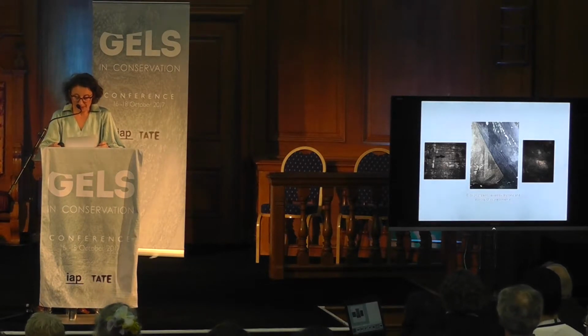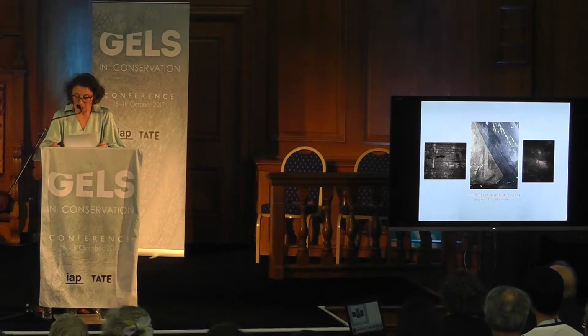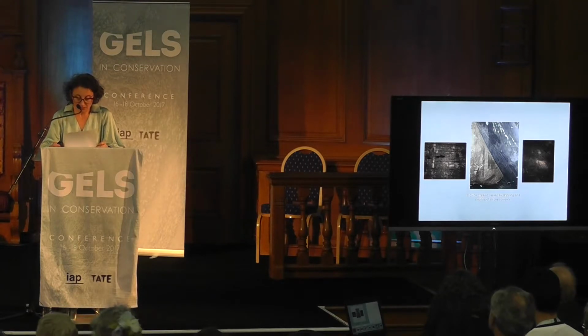The material characteristics of the altarpiece posed many challenges to the cleaning. The very delicate original paint lacks the hard qualities of an oil-based paint film. Through empirical observation, it has been found that the paint film is softer than what we would expect of an oil paint of this age. Softening of dry oil-based paint layers can be attributed to saponification, when soaps or salts of fatty acids are formed by the hydrolysis of ester linkages and triglycerides under alkaline or acid conditions.